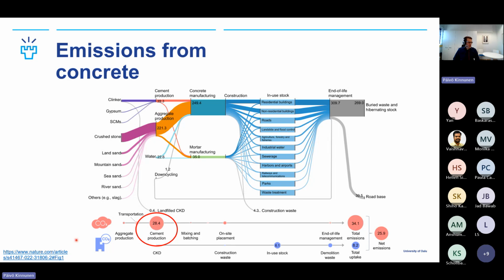And CO2 emissions here at the bottom. So this is basically starting materials, and then the material flows, where do they go? Then we have construction in stock and end of life management. And in terms of the CO2 emissions, most of it by far comes from the cement production, and not from the stone production, even though that's 80-90% of the mass or volume, but it's the 10% that's cement that causes over 90% of the emissions. So clearly, if we want to reduce CO2 emissions in cement or in concrete or construction, cement is one of the main issues to look at.